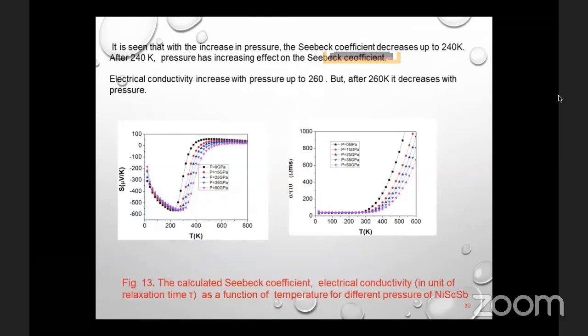For the optimum doping concentration, the temperature dependence of the Seebeck coefficient and electrical conductivity under different pressures are also given in Figure 13. It is seen that with the increase in pressure, the Seebeck coefficient decreases up to 240 Kelvin. After 240 Kelvin, pressure has an increasing effect on the Seebeck coefficient. Electrical conductivity increases with pressure up to 260 Kelvin, but after this temperature, it decreases with pressure.